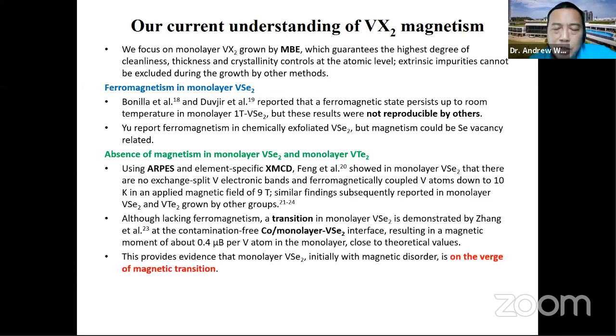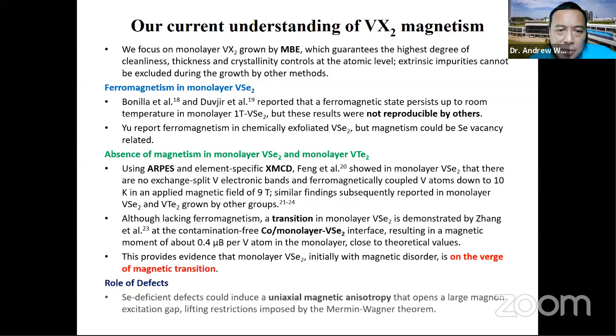So we conclude that it's on the verge of magnetism, and the role of defects could induce uniaxial magnetic anisotropy. As I mentioned before, anisotropy is very important because it opens a magnon gap. It lifts restrictions imposed by the Mermin-Wagner theorem, and hence you can make a 2D material magnetic.